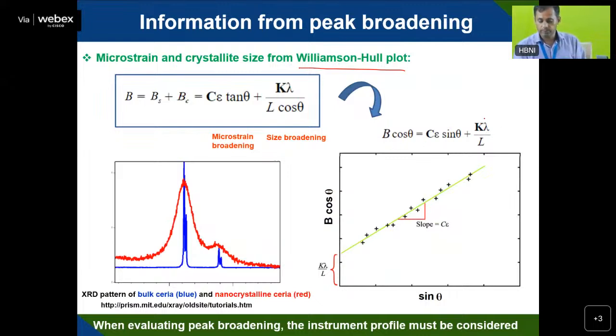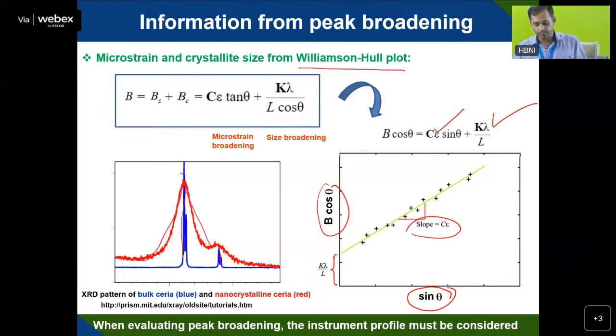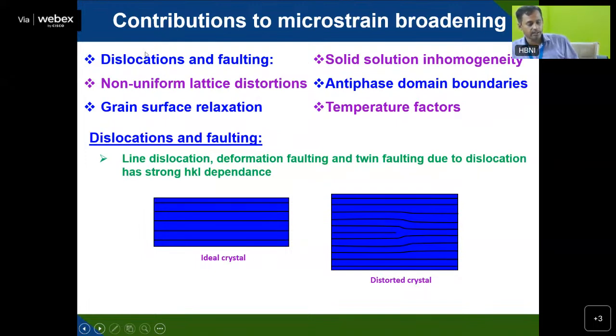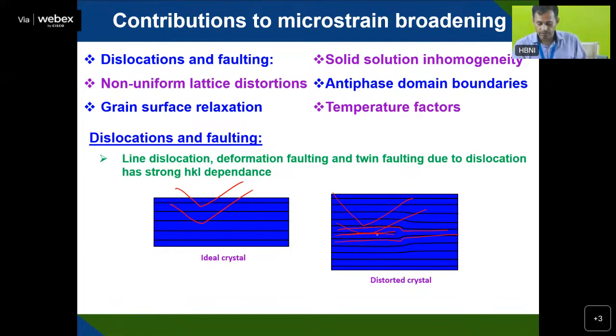Using the Williamson-Hall plot, the broadening β can be separated into crystallite size and lattice strain contributions with higher accuracy. You can see that in the bulk form you get sharp peaks, whereas in nano form the broadening is evident. This broadening is due to either crystallite size or lattice strain. Additional factors that contribute to strain include dislocations, stacking faults, ideal crystal distortions where an additional plane is inserted, and atomic misplacements causing strain in the system.